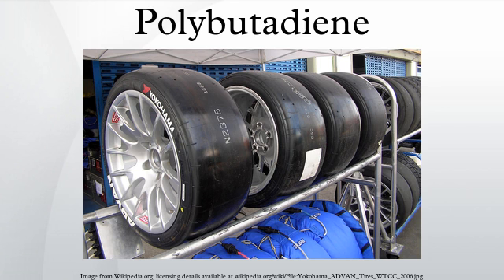In addition to these three kinds of connectivity, polybutadienes differ in terms of their branching and molecular weights. The trans double bonds formed during polymerization allow the polymer chain to stay rather straight, allowing sections of polymer chains to align to form microcrystalline regions in the material. The cis double bonds cause a bend in the polymer chain, preventing polymer chains from aligning to form crystalline regions, which results in larger regions of amorphous polymer. A substantial percentage of cis double bond configurations in the polymer will result in a material with flexible elastomer qualities.